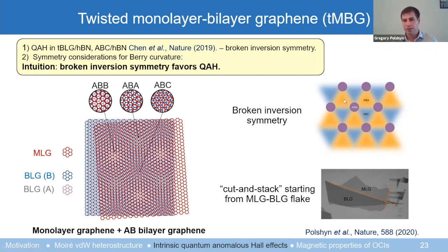But it can also be seen if we look at the distribution of local stacking in the plane. There are regions with local ABB stacking, which form a triangular lattice, and electrons often tend to reside on these sites. But then there are two qualitatively different types of interstitial sites with either ABA or ABC stacking.